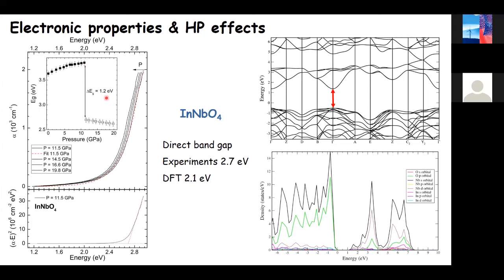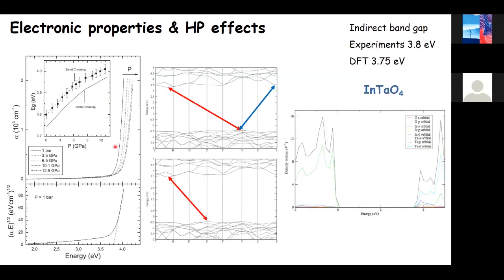If you go to the other compound, we observe the same. Indium tantalate has 2 indirect band gaps. It blue shifts under compression. The band gap is again large, and you see 3.8 eV at ambient conditions. It increases with pressure. There is a crossover between the two minima of the conduction band, and then the slope changes.